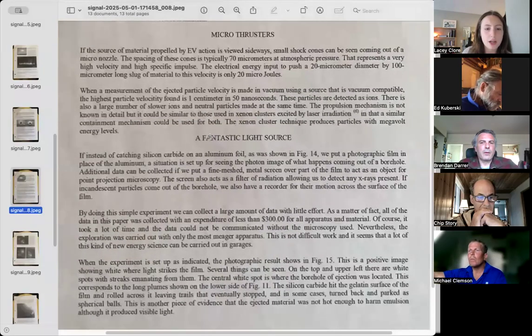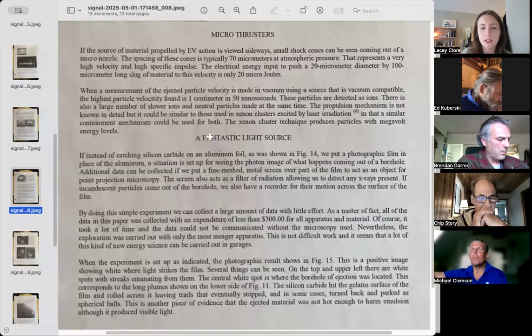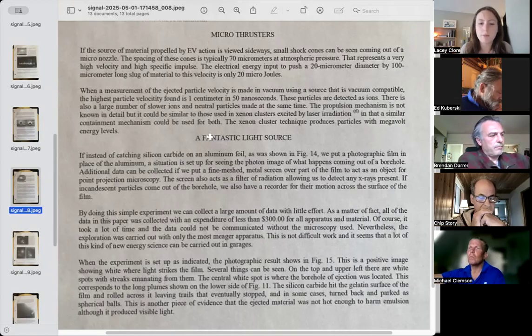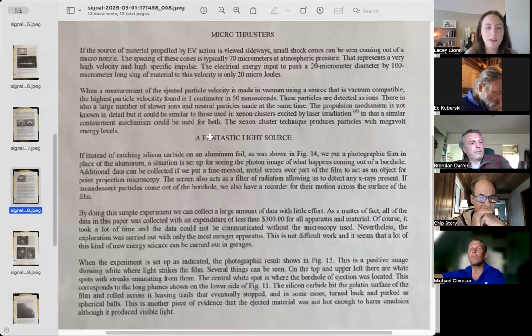When a measurement of the ejected particle velocity is made in vacuum using a source that is vacuum compatible, the highest velocity found is 1 centimeter in 50 nanoseconds. These particles are detected as ions. There is also a large number of slower ions and neutral particles made at the same time. The propulsion mechanism is not known in detail, but it could be similar to those used in xenon clusters excited by laser irradiation, and a similar containment mechanism could be used for both.